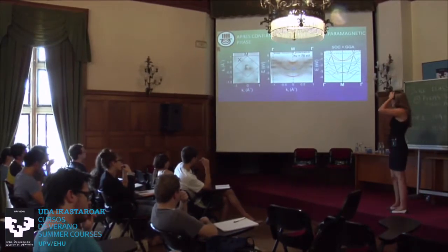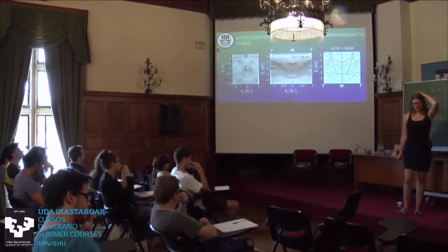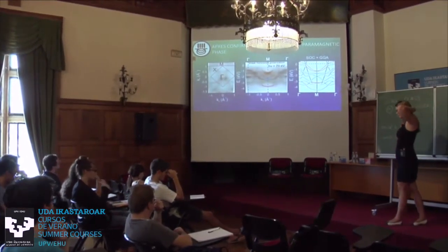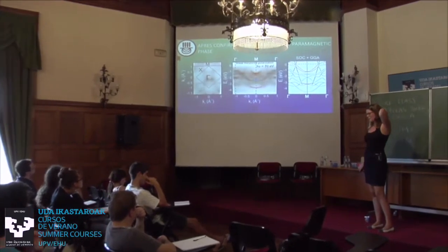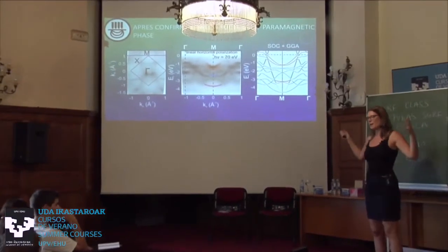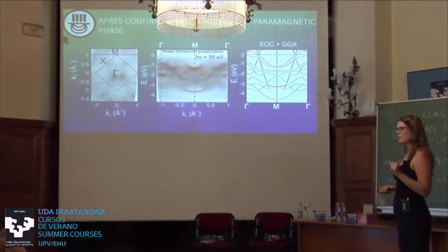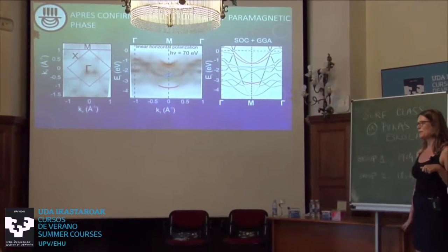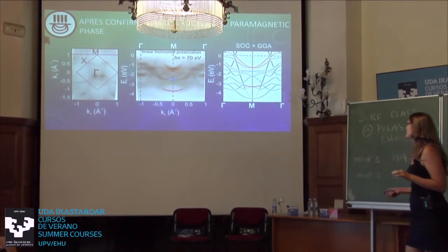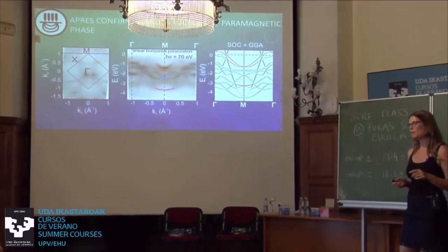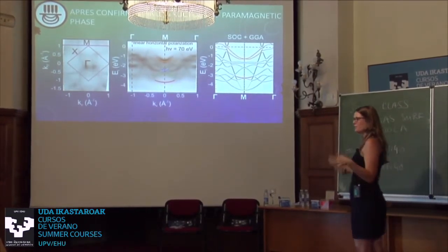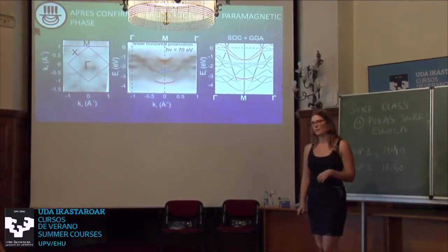And then lastly, this was all theory so far, and this was an experimental talk, so we also did some ARPES experiments. The problem with ARPES is that it's not really applicable in a ferromagnetically ordered phase or where a field is aligned, because the electrons you eject are going to be deflected by the field. So this would be something for an STM experiment, and maybe Chaim will talk about this possibility tomorrow. But we did some ARPES on the paramagnetic phase where we don't have any magnetic order, and we could confirm the basic features in the electronic structure to be sure that we at least didn't make a complete random prediction here.